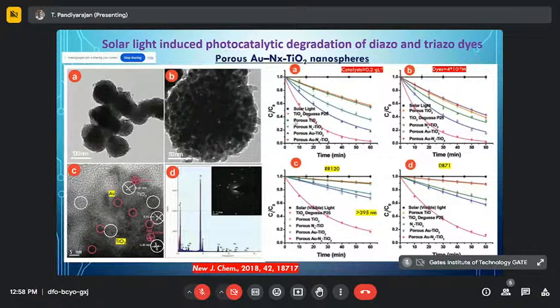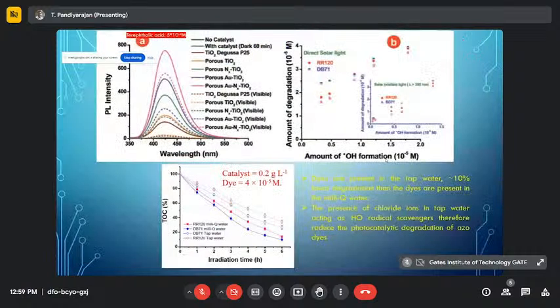And when we use porous titanium dioxide alone without any doping, then it has slightly increased efficiency. But when I add nitrogen as a dopant, it is increased further. When I use gold nanoparticle doped titanium dioxide, it is increased further. But when I combine these two, titanium dioxide along with gold and nitrogen, the degradation process is highly efficient. Okay, then we varied with two different dyes, and we have verified, and it was identified that direct sunlight is highly usable, and it directly converts those diazo and triazo dyes into usable chemicals like water and carbon dioxide.